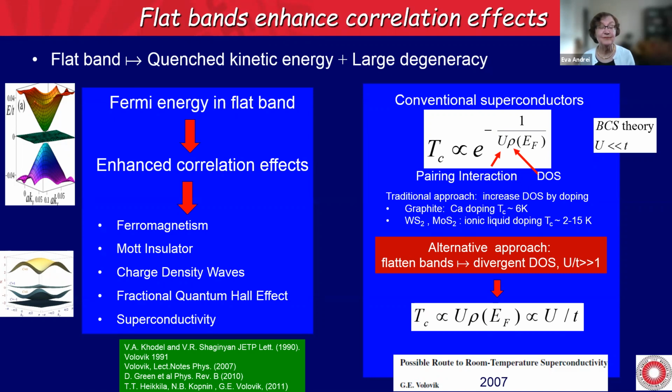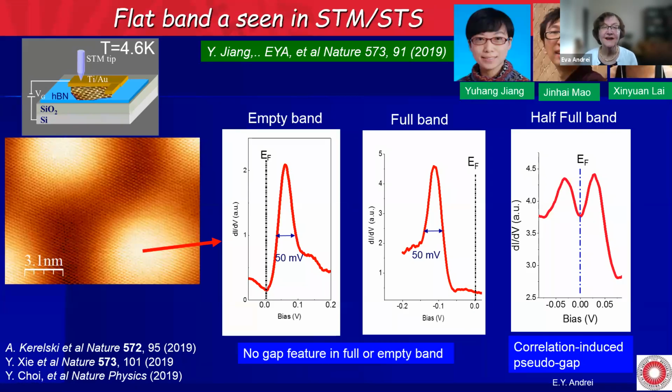So we measure density of states, and we know where the Fermi energy is. We know where the band edge is. Let me get to that slide. Okay, here. The density of states is a function of energy, with the Fermi energy sitting here. If I integrate from the band edge to the Fermi energy, I know what fraction of the band is occupied and what fraction is empty. And we know that there are 8 electrons per Moiré cell, so 8 electrons per Moiré cell will fill the entire band. That allows me to calculate the charge by just taking the integral here.